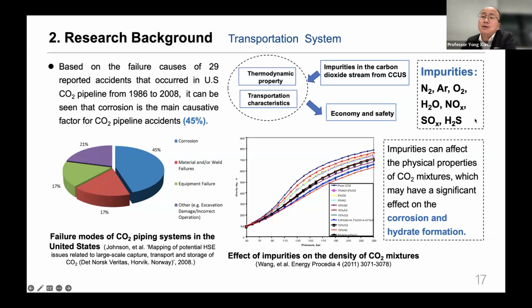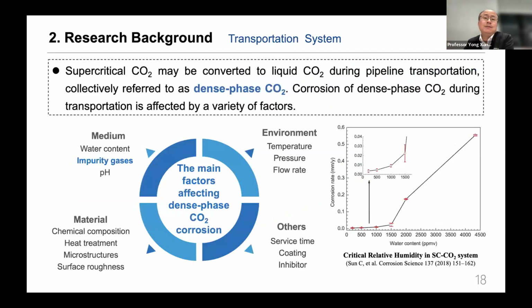So as we all know, there are a lot of impurities inside the CO2. If they come into the CO2 pipeline, they may have some impact on the physical properties of the CO2 mixtures. And in the end, they will have an effect on corrosion and hydrate formation. The corrosion problems also have a lot of influence factors, including the medium, the materials, environment, and others. For the medium, it depends on what the CO2 has inside. That is the impurity gases, what kinds and concentrations of impurity gases, especially the water content.